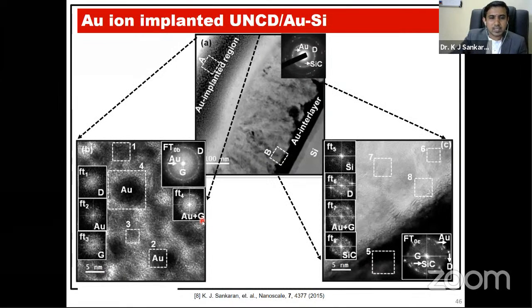So gold acts as a catalyst to induce the nanographitic phases in the diamond. Also, you can see here, this is the interface region, and there is the presence of some silicon carbide between the UNCD and the gold. So silicon is interdiffused inside the gold and forms some silicon carbide clusters in nanoparticle sizes that will enhance the electron transport between the silicon and the UNCD, which achieves a low turn-on field.